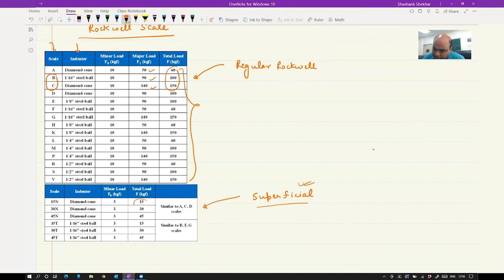If you see here, the regular one was of very high load, starting from 60 kgf and going up to 150 kgf. Here in superficial, it starts at 15 and stops at 45 kgf. The scale names are 15, 30 and 45, and the indenter will be a diamond cone. And when we have T, then it will be a steel ball. Minor load is also reduced, from 10 to 3, when we have the superficial scale. I have listed only some of them. You have many more scales, say W, S, and Y, when we talk about the superficial Rockwell scale. So this is what I wanted to discuss about hardness testing, especially the indentation on Rockwell, Vickers, and Brinell.